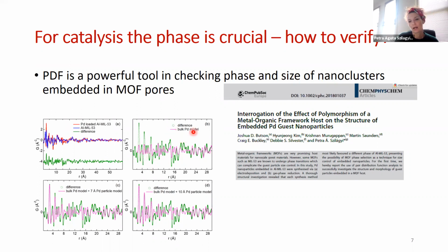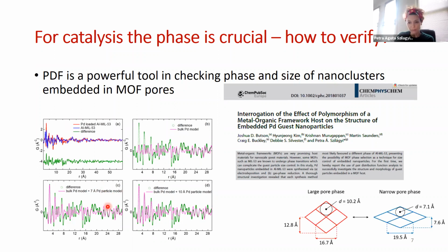And so what we did is we tried to fit the face-centered cubic crystal structure of the bulk palladium. As you can see, the peak positions are a very good fit, and the problem is really with the intensity. That is, of course, because the particle size is much smaller. Refining the model, we were able to determine that the typical particle size was around 7 angstrom. And that, in turn, allowed us to determine which of the 2 possible polymorphs of this framework is used as the template for the growth of the palladium nanoclusters in this case.